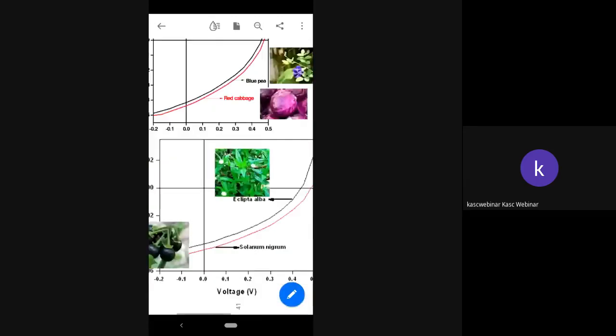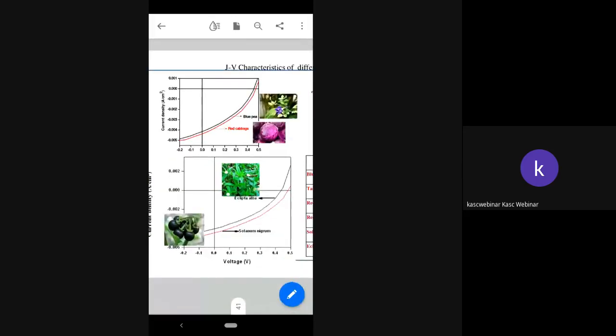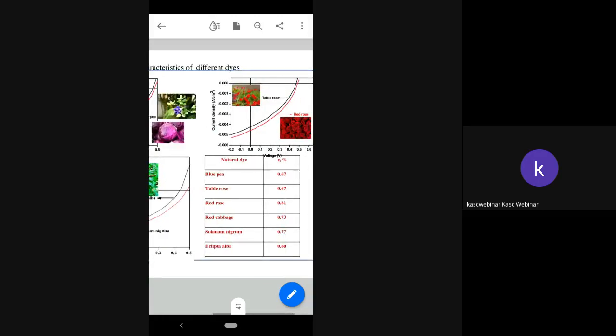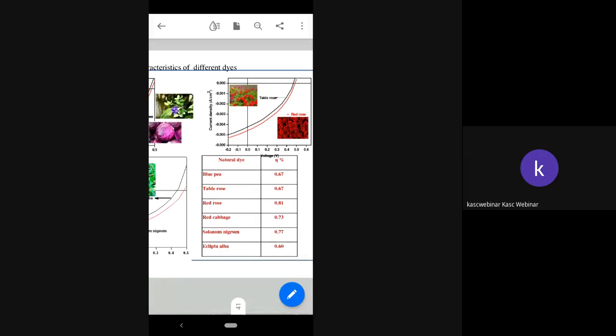And in the third graph, we have sensitized the TiO2 using Eclipta alba, locally called as Karisilangani, and the red line corresponds to Solanum nigrum, locally called as Manathakkali Keerai. And the table shows the efficiency of these different dye sensitized solar cells. Moreover, we have obtained the efficiency around 1%, even though we have varied the dye sensitizer. And even though this type of solar cell devices are eco-friendly, the efficiency was low. Because of this reason, we have moved on to the next generation, that is the evolution of perovskite solar cells.